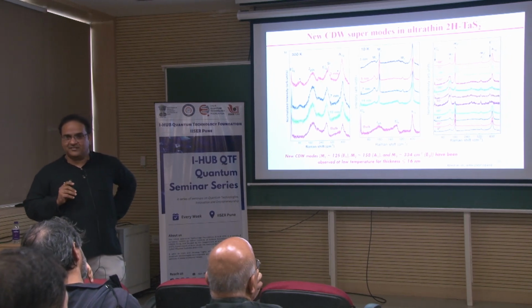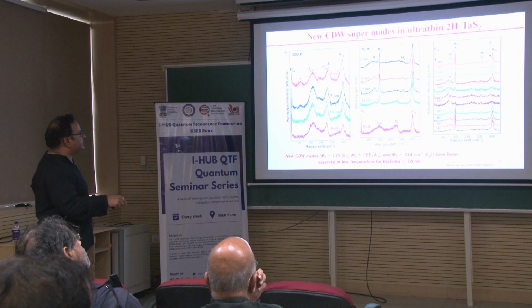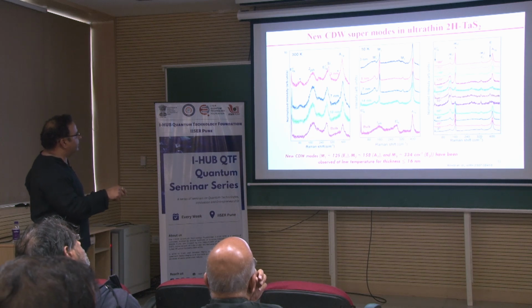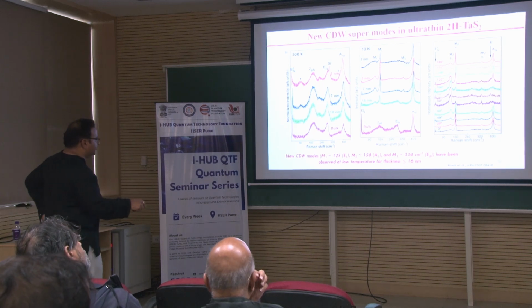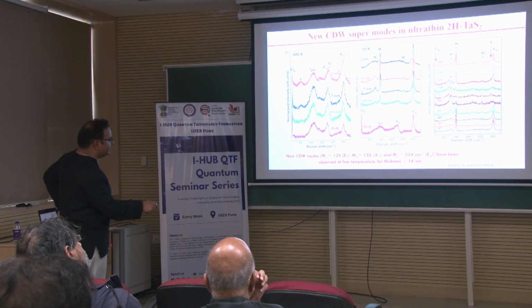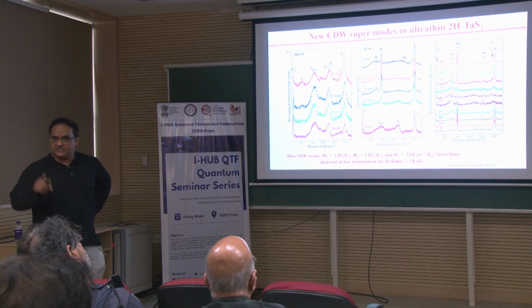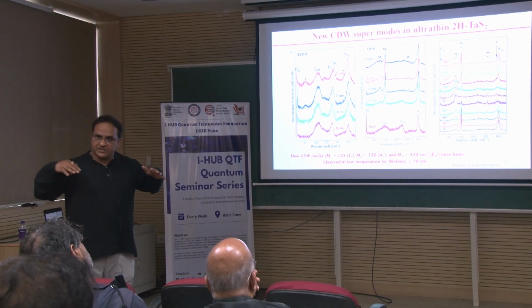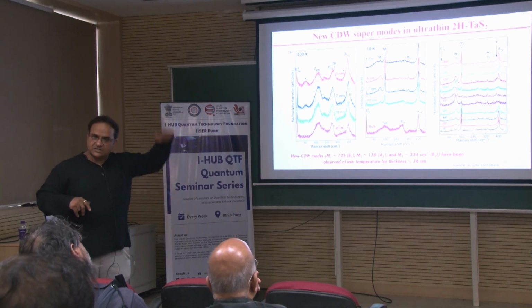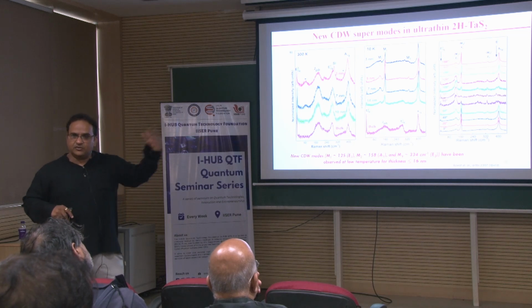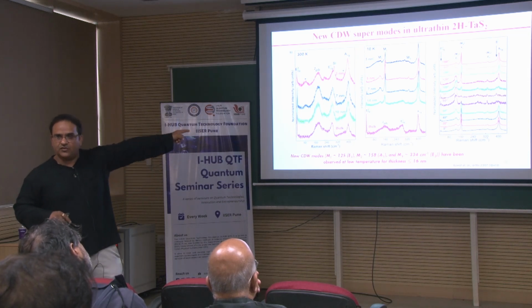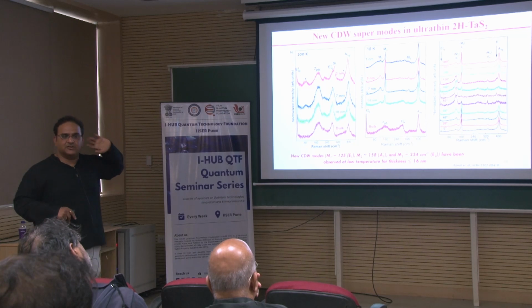And what was the conclusion from here? We just wanted to know the symmetry of this M1, M2 and M3. Okay, so M1 is E symmetry, M2 is A symmetry, M3 is E symmetry, which means M1 and M3 have in-plane vibrations. On the contrary, M2 has out-of-plane vibrations, and these out-of-plane vibrations have more electron phonon coupling involved. That's the conclusion from this one.